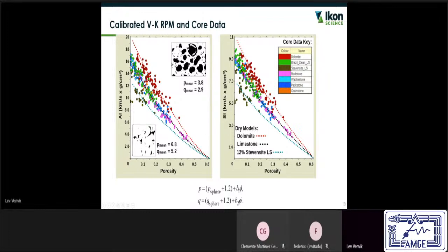There might be much more crooked pore shapes, such as, for example, this. These are not pores that can be described by any kind of aspect ratio, because there are some popular models that operate with aspect ratios and include these models. But there are some pores that really don't lend themselves to aspect ratio analysis, because for instance, an equilateral triangle and a sphere will have about the same aspect ratio, but vastly different compliance characteristics.